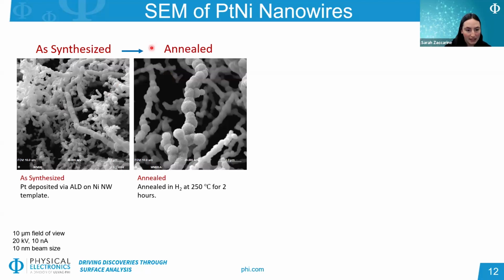After annealing, we retain a lot of that structure. We start to see there's some textural differences on some of these different wires. Some of them are slightly more smooth. Some of them have a little bit of roughness on these wires. And this annealing process was again done to alloy the platinum with the nickel metal. So this was done in hydrogen at 250 degrees C for 2 hours. So we're going to be looking a little bit more at the chemistry implications of that in a bit.